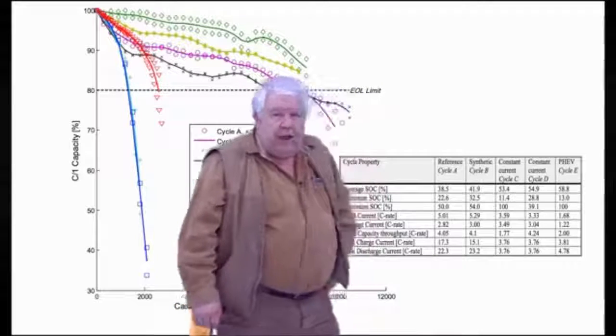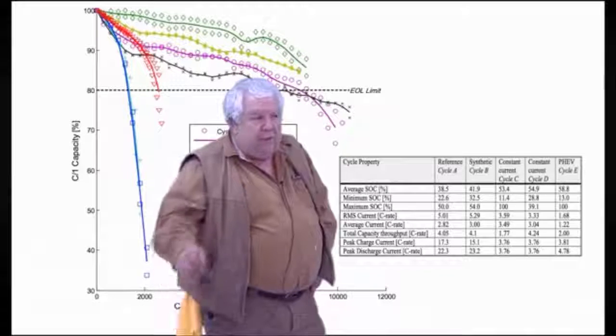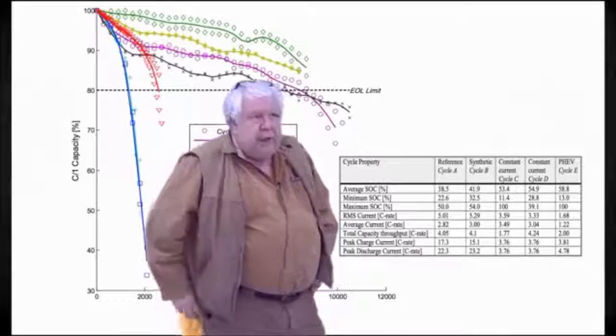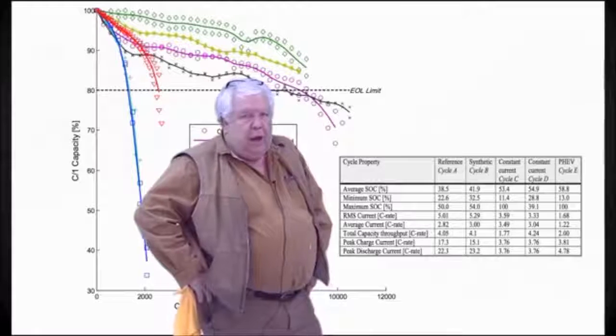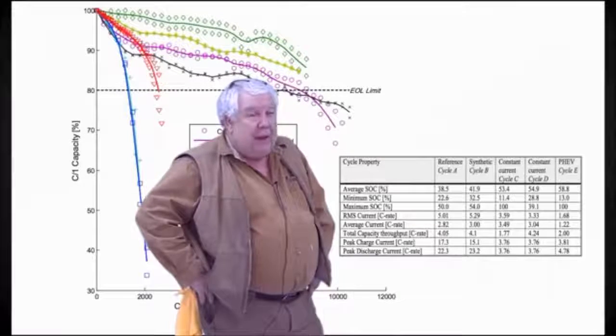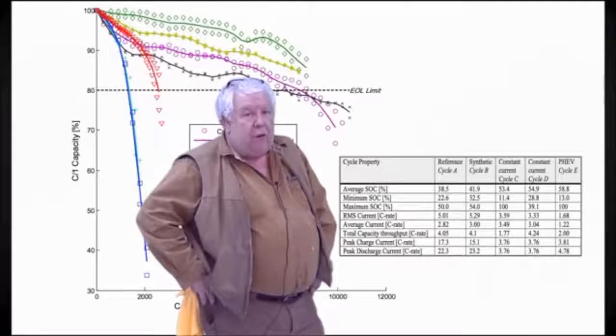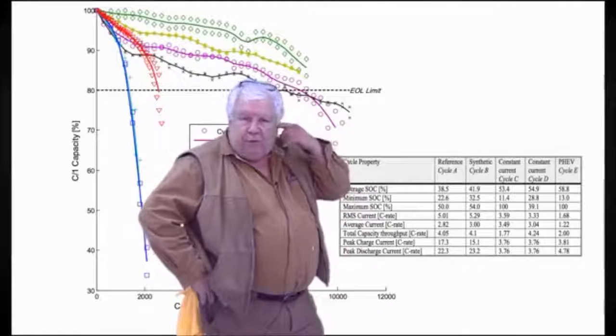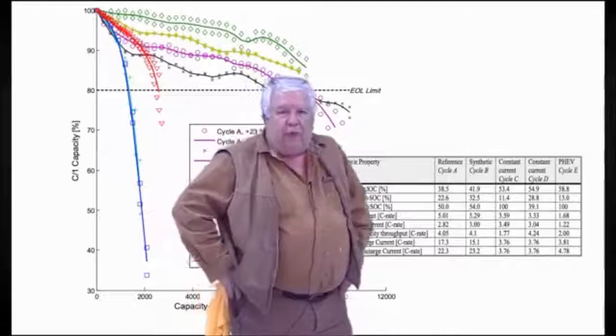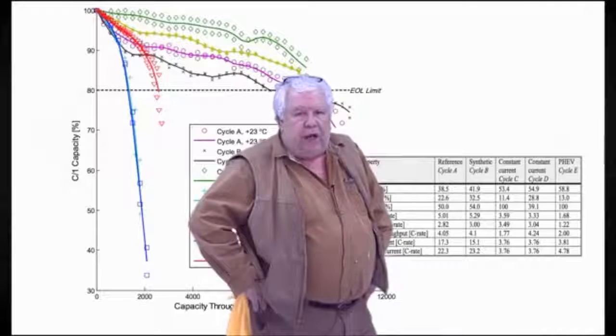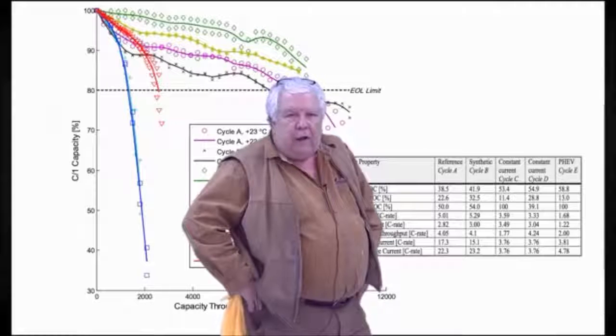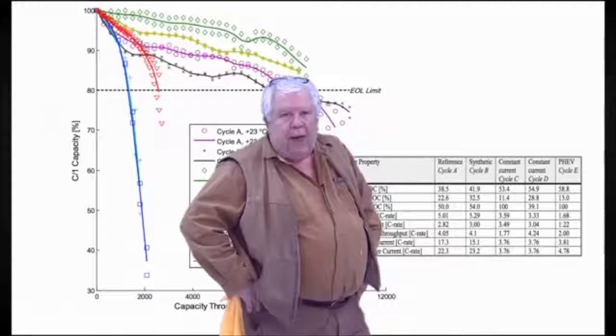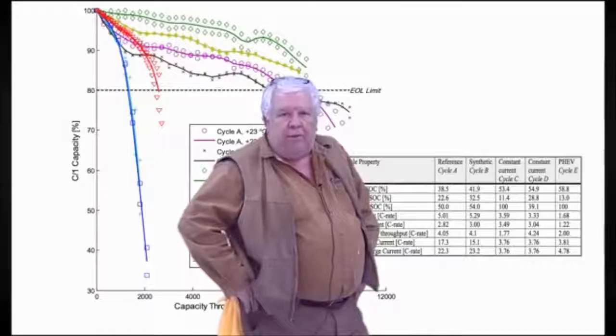Again, the trick is not to over-discharge and not to overcharge. We bottom balance the cells to prevent damage in over-discharge, and we undercharge the cells slightly. I would say if cycle life is your main criteria, and it's certainly up there for me, I don't need the range, I need the batteries to last a long time, it would be perfectly permissible to drop your charge voltage, not even to Jack's 3.55, but let's say 3.4, the open circuit voltage of the cells, and charge them to 60% or 70%, and then stop them in all cases before they get below 20%. These cells could literally do 10,000 cycles. If you do 300 cycles a year, that's 30 years that the batteries will last. And I believe it's entirely possible.